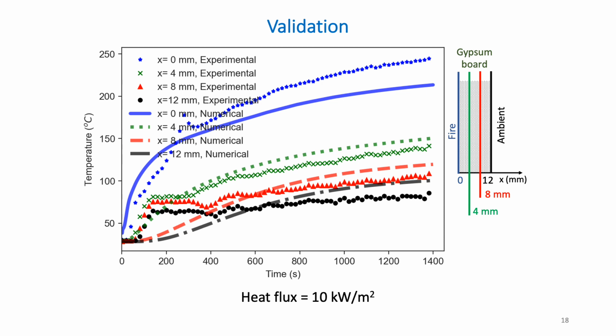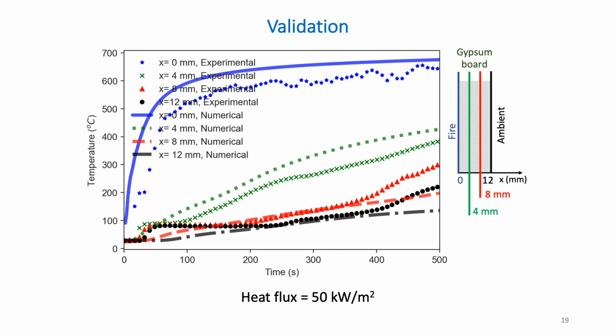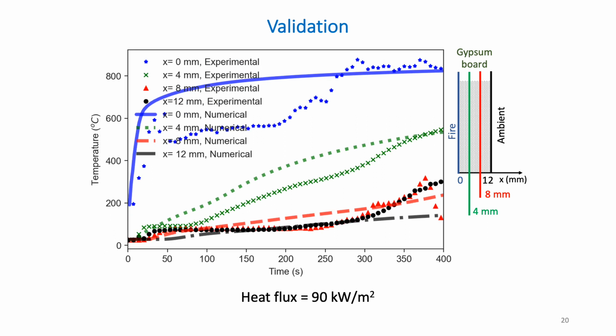Set a lower heat flux of 10 kilowatt per meter square. We see reasonable agreement, and most of the numerical predictions are within the experimental uncertainty. The same trend continues, even at very high heat fluxes, where the fluctuations in the surface temperature are significantly higher. Despite that, internal temperatures are reasonably well predicted.